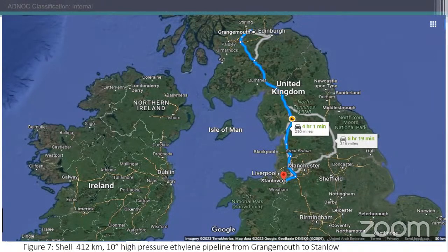So this probably must have been a result of something else. They believed the cause was likely still there. So they started investigating, and they introduced corrosion coupons and monitored the coupons. They checked the alternating current. They checked the facilities they had around. They had a high voltage transmission line of very high capacity laid along this pipeline.